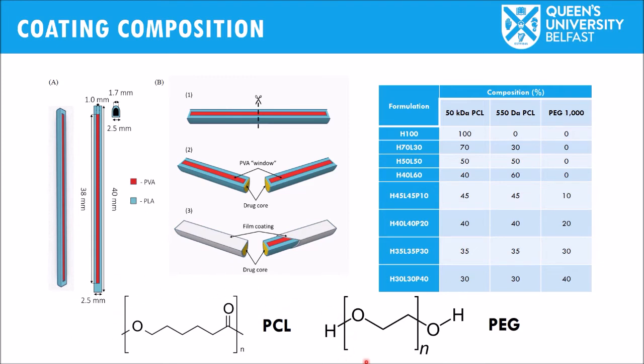But different types of polycaprolactone were used. We use high molecular weight polycaprolactone, and we combine it with a low molecular weight polycaprolactone, and in some formulations we included polyethylene glycol. Okay, the different combinations of these polymers gave different properties to the membranes in terms of porosity and drug permeability.